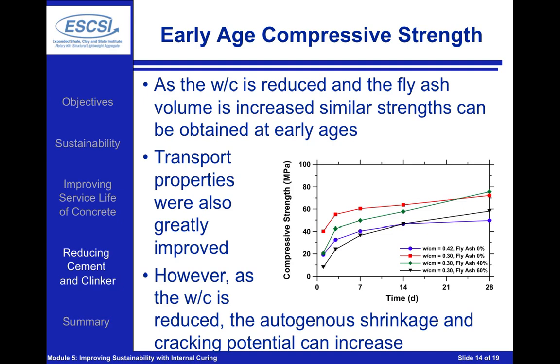And this is obtained by not only just replacing the cement, but by also altering our water to cement ratio. In addition, by altering our water to cement ratio, we're able to greatly improve our transport properties because, as we know, as we reduce the water to cement ratio, we're going to cut down on fluid flow in those systems. However, as we've seen in our previous modules, reducing the water to cement ratio is going to increase the autogenous shrinkage, and it's going to increase the potential for cracking. So this is really where you can start to see where the benefits of internal curing are going to be in this system. By using a lower water to cement ratio, we're able to replace a larger proportion of the cement.